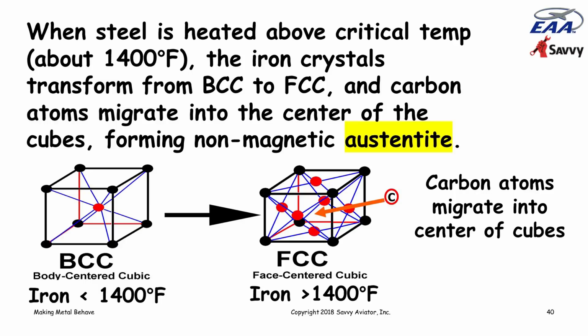When we heat the steel up above the critical temperature, the cherry red temperature, about 1400 degrees, and the iron transforms from body-centered cubic to face-centered cubic, there's no iron in the middle of the crystal, and carbon winds up migrating into the center of these little crystalline cubes. And that forms a material that's called austenite, but it only exists when the steel is heated to cherry red temperature. Austenite doesn't exist at room temperature.